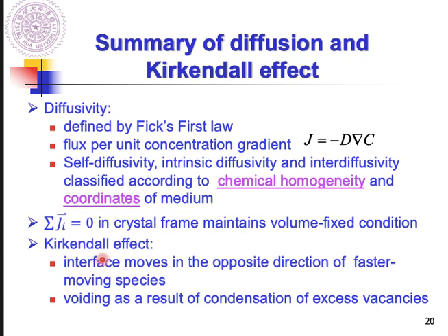The first one is the plane shift. It's going to shift in the opposite direction of the faster moving species. And the second one will be the void formation. That will be the result of condensation of excess vacancies, which means the vacancies will accumulate and grow to form a void.